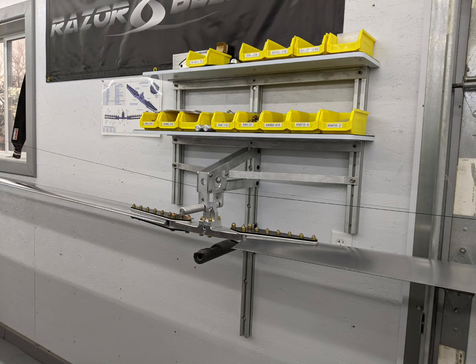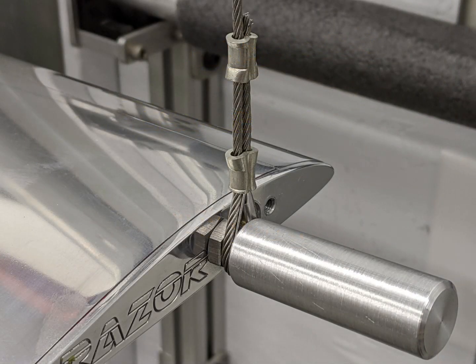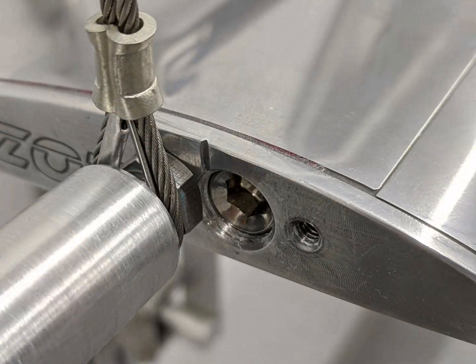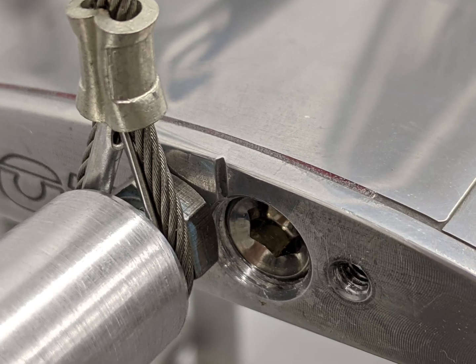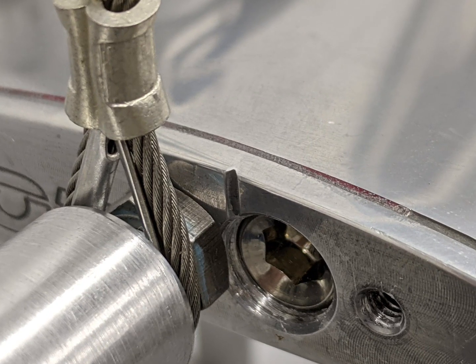The first step in blade calibration is the blade stringing. We use a method where we support the hub bar, much like it'd be mounted onto a rotor head. The ends of the blades are supported via cables mounted above. These are precisely plumbed to the end of the blade, and they hold the blade in a very natural position without applying any side forces or twisting of the blade. The end caps of our blades feature a nice little machined groove for alignment of the string during this process.